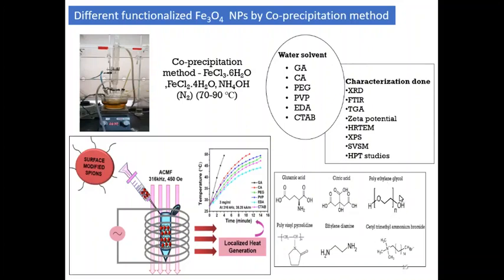Then we have polyethylene glycol, which generally provides steric stabilization. Then there is polyvinyl pyrrolidone, then ethylenediamine, a diamine functionalization, and there is CTAB functionalization. In the CTAB we have a methyl group, and here a nitrogen plus group is there. All right. Then finally we did the hyperthermia, temperature rise versus time.